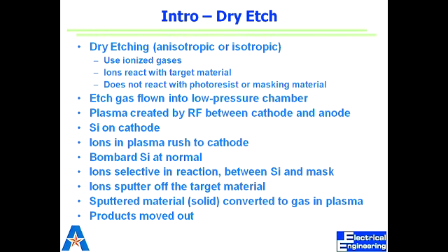That plasma's ions are bombarded on the substrate, and after bombardment, due to the film to mask selectivity, there is a reaction between the film and those plasma ions. Those byproducts are very volatile and they are removed by the carrier gases. Those carrier gases are mostly inert gases. It may be nitrogen, it may be argon, or some other inert gas used as a carrier gas. So this thing we have discussed last time. This is just a representation of the flowchart of how the dry etching works.